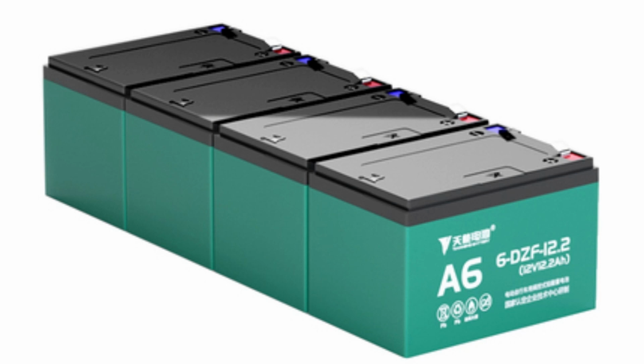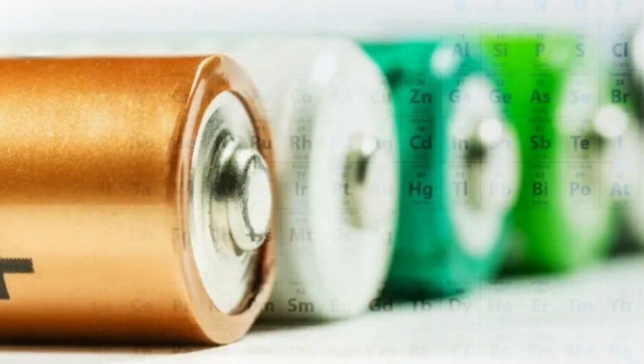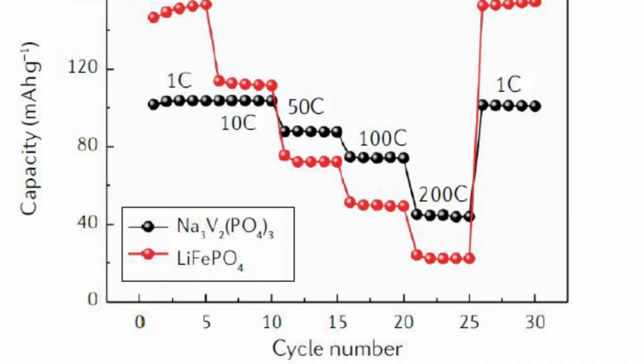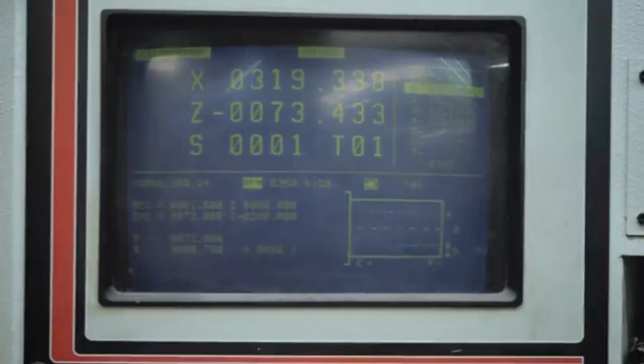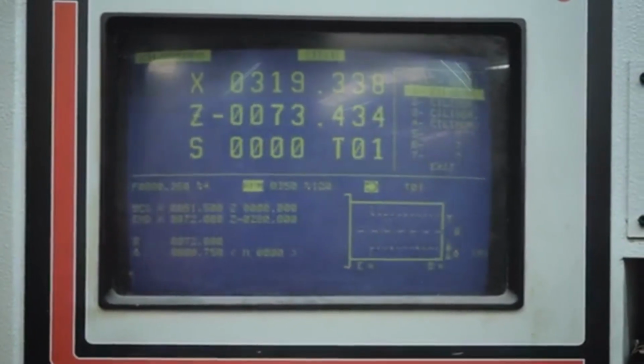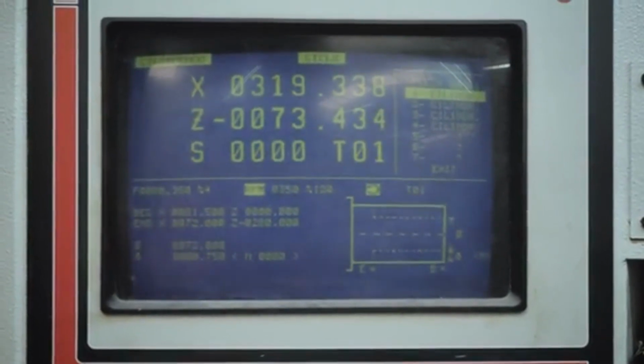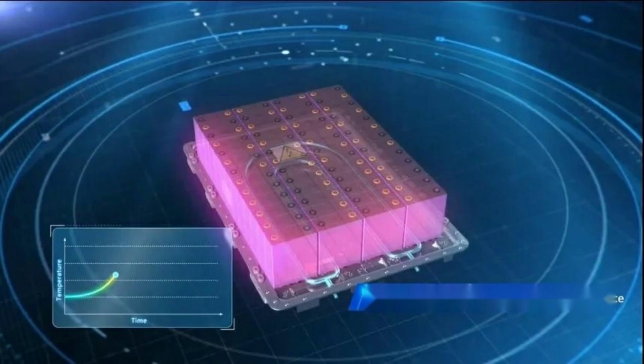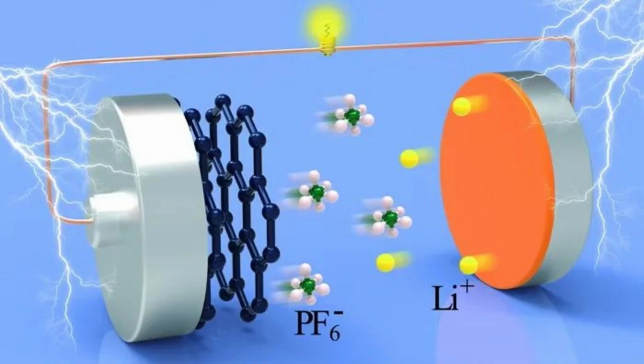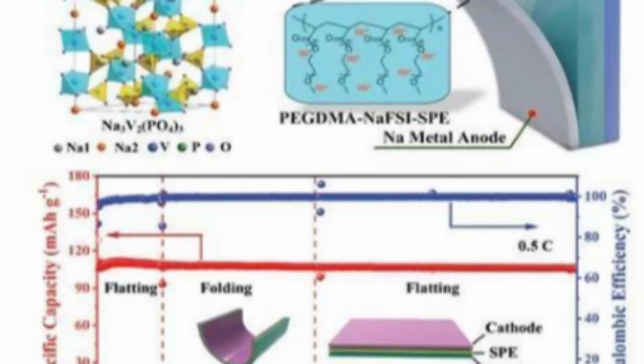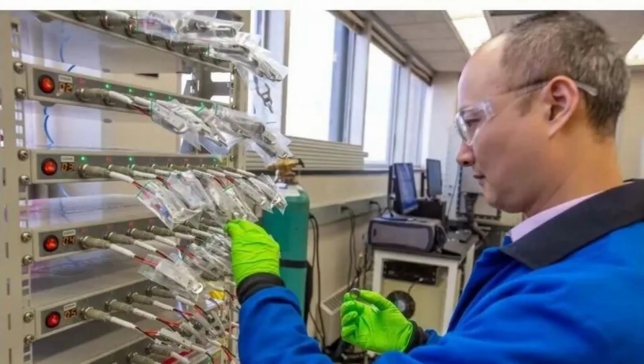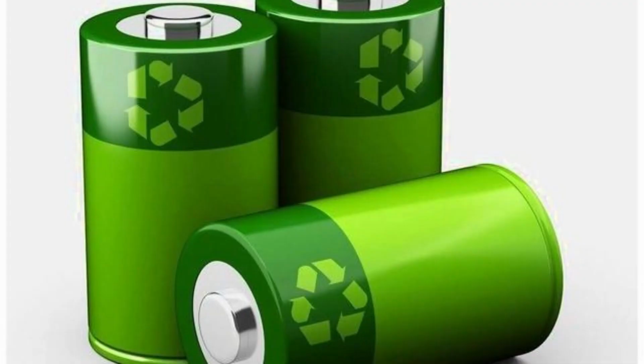Sodium-ion batteries have better high and low temperature performance. Compared to lithium-ion batteries operating in the temperature range of -20°C to 60°C, sodium-ion batteries can operate normally in the temperature range of -40°C to 80°C, with a capacity retention rate of nearly 90% in the -20°C environment. Sodium-ion batteries have higher safety. Thanks to higher internal resistance, sodium-ion batteries have less instantaneous heat generation under short-circuit conditions, and the temperature of thermal runaway is higher than that of lithium-ion batteries, providing higher safety. The safety performance of sodium-ion batteries is also satisfactory when tested for overcharging, discharging, puncture, and squeezing.